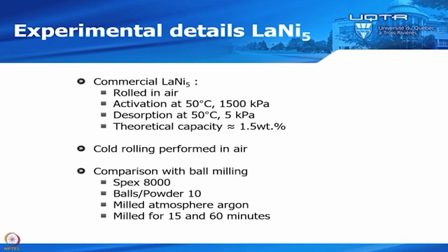So the example that I will show you today is lanthanum nickel 5. So cold rolling of lanthanum nickel 5. So we took commercial lanthanum nickel 5, we roll it in air, and after rolling, we do the first hydrogenation, the activation at 50 degree and 15 bar, and the desorption was also done at 50 degree and 5 kilopascal. And the theoretical capacity of lanthanum nickel 5 is about 1.5%. And again, I have to stress that the cold rolling was done in air.